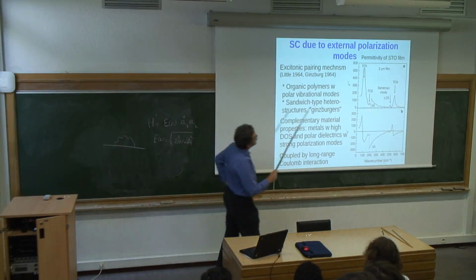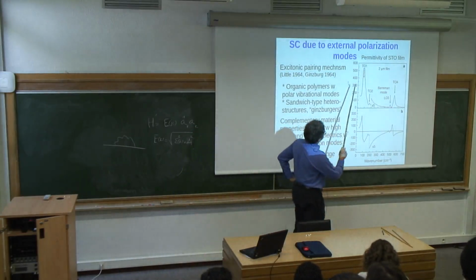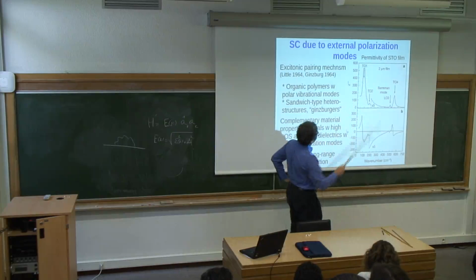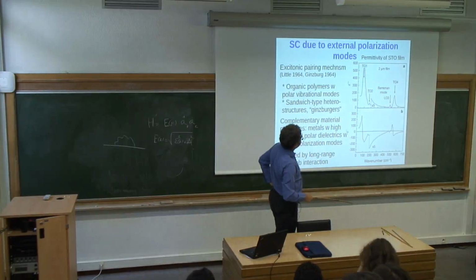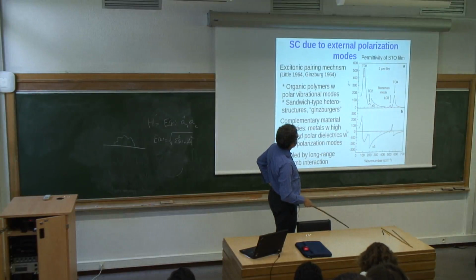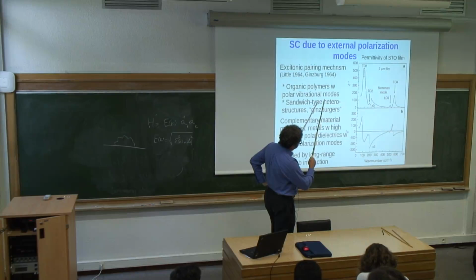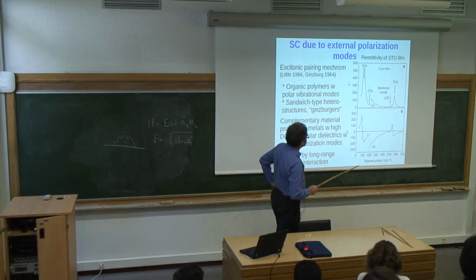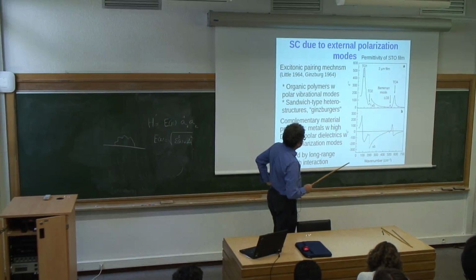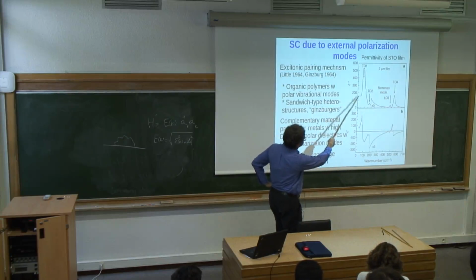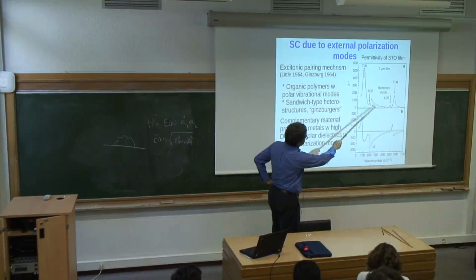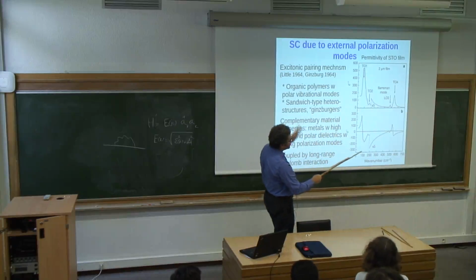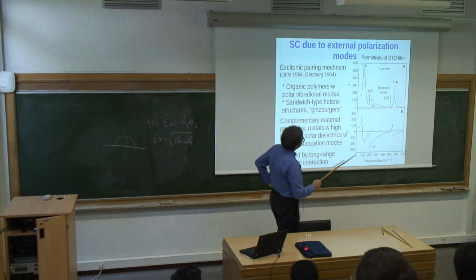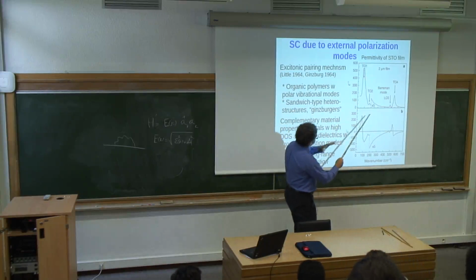So, for example, if you take one of the very polar dielectrics, strontium titanate, this is the permittivity frequency dependence, optically measured. Then this is absorption. These resonances each can be modeled as a single resonance by this formula that was in the previous viewgraph, and the width is due to damping.